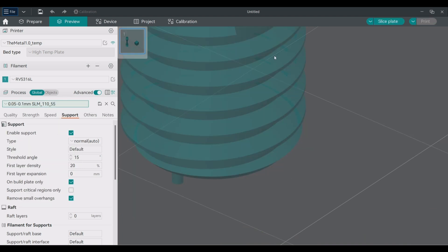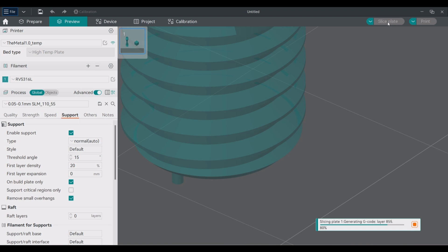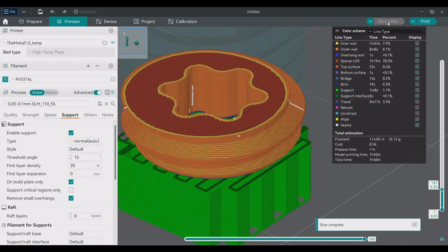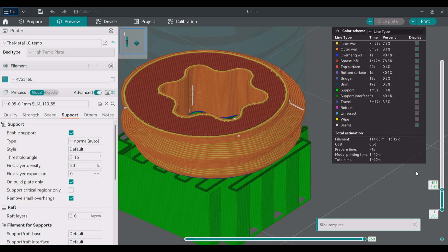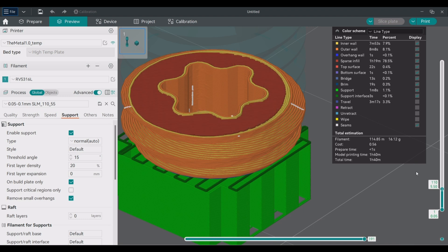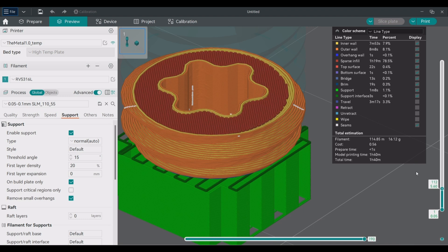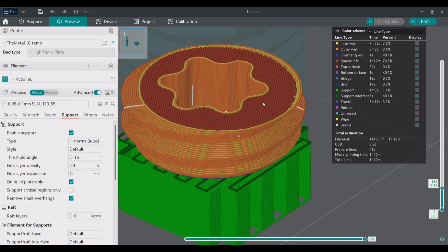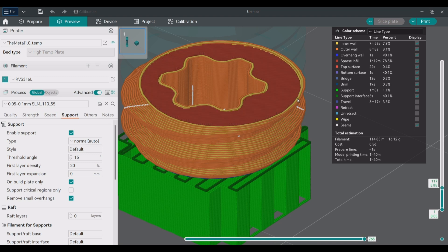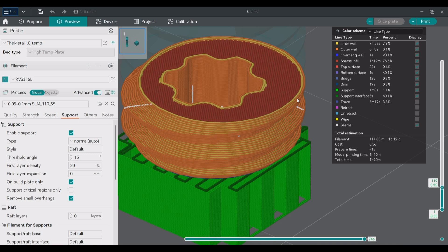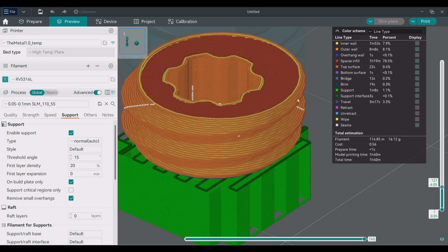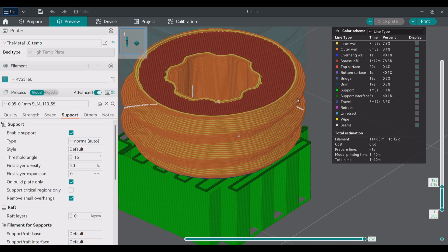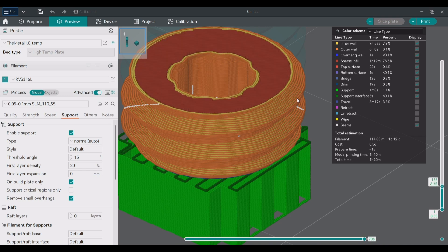Now I will show you the other print profile. In this profile the infill is only printed every two layers instead of every layer. This can improve the print speed quite a bit but it will result in a few percent less density. You can see the predicted print time has reduced from 2 hours and 11 minutes to 1 hour and 40 minutes. In the preview it also becomes clear that now the infill is not printed every layer but every other layer while the walls are printed just like normal every layer.